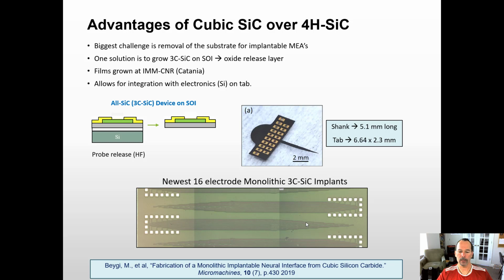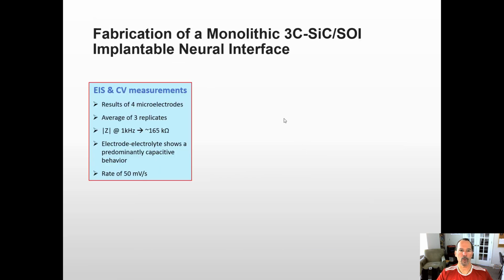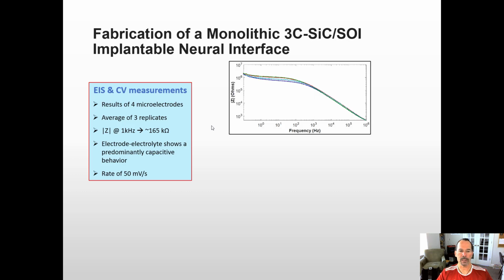And that should be reported at the next conference, hopefully. So what do we have so far for data? Using the same planar MEA, we see that we have nice impedance performance. We have a lower impedance for the smallest area. Before it was in hundreds of kilo ohms, now we're about 165.